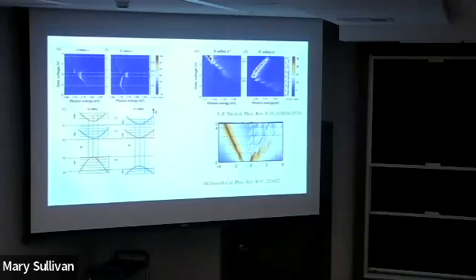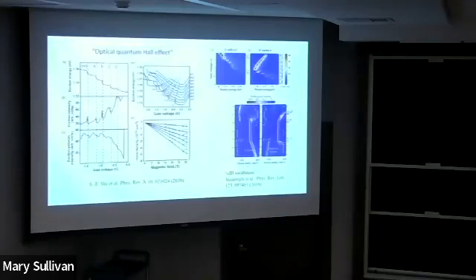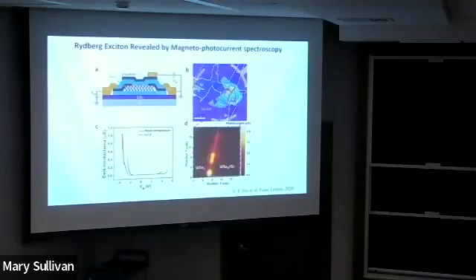So one thing we can propose is that to form this exciton, you actually need tens of electrons from these Landau levels, and you need tens of holes from these Landau levels. So what you have is not really a simple electron-hole pair. You actually have many Landau levels in the valence band and many Landau levels in the conduction band forming this quasi-particle. How to understand this, we don't know. But experimentally, what you see is essentially quantization of the exciton energy. And if you plot the energy, it very much looks like the quantum Hall measurement. Well, you see these plateaus, right? And I'll just leave it like this. This we published last year, and I'll try to move on a little bit.